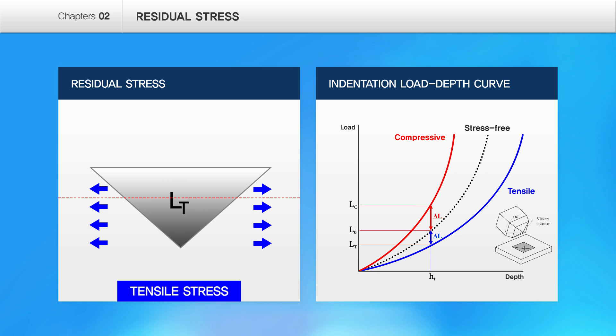This means less load is needed to get the same indentation depth. On the contrary, if the same material, but squeezed by compressive stress from the sides, is being indented, its maximum indented depth is reduced with the same load applied.